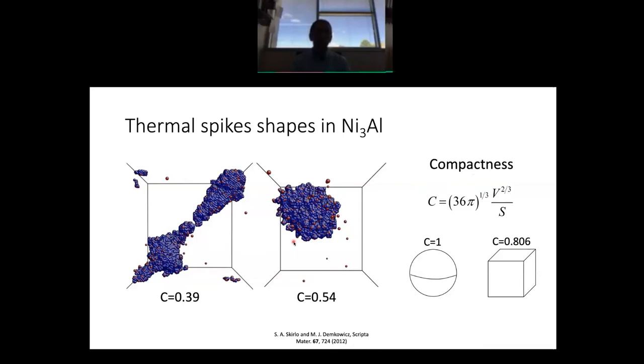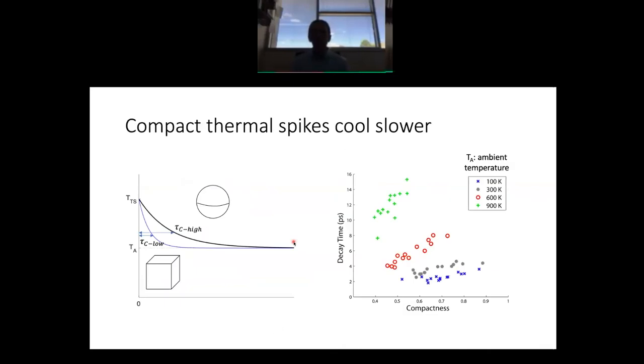Now, what does compactness do to a thermal spike? Well, it changes the rate at which it cools. In particular, thermal spikes that are compact, right, that have high compactness values, cool more slowly. They have less surface area per unit volume, so their cooling rate is slower. Conversely, thermal spikes that have a low compactness cool faster. So, if I were to plot the temperature inside a thermal spike, let's say it starts out here, and then over some time it cools to the ambient temperature, T sub A, the decay time of this temperature for a compact thermal spike like a sphere is going to be large. The decay time for a less compact thermal spike, like let's say this cube, is going to be relatively shorter. So we actually measured these decay times for all these thermal spikes, and we plotted the decay time versus the compactness. And indeed, the more compact a thermal spike is, the longer its decay time.